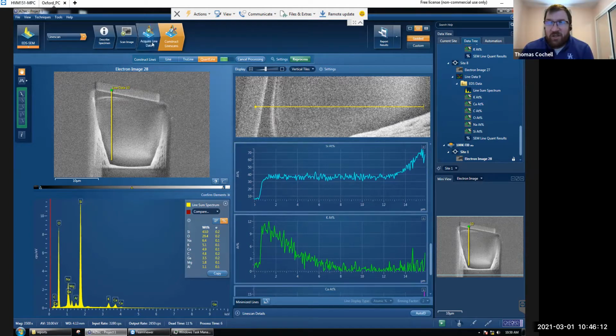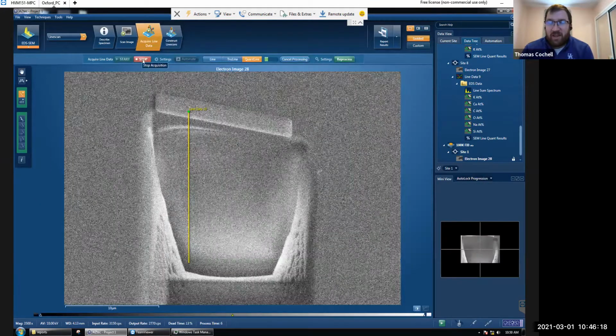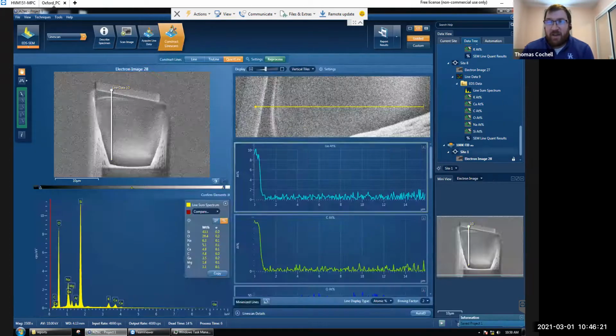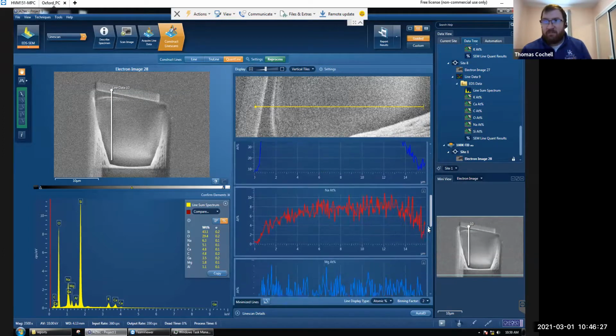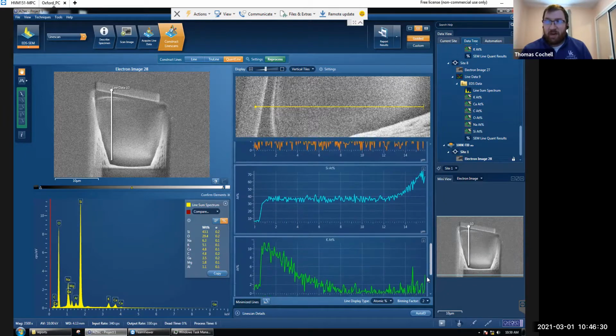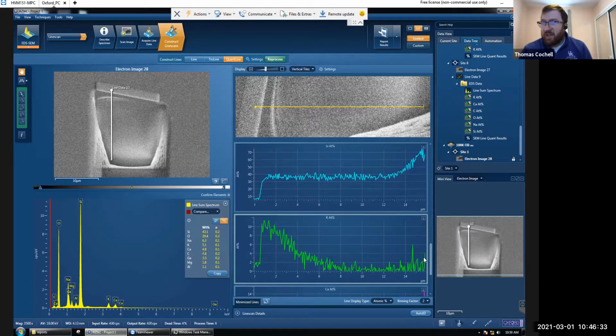Yeah, and what you mentioned earlier, and I think after they get some of the images, that they can look at those cross sections that we did, and yeah, the gap, which might indicate some of the crushing or some of the effect from mechanical grinding and polishing, was on the order of what, 10 to 20 microns, something like that. Yeah. And it looks like we're seeing less than 10 microns on this sample, so that's a good start, at least in explaining what's happening. Yeah. Well, I'm glad that worked out.